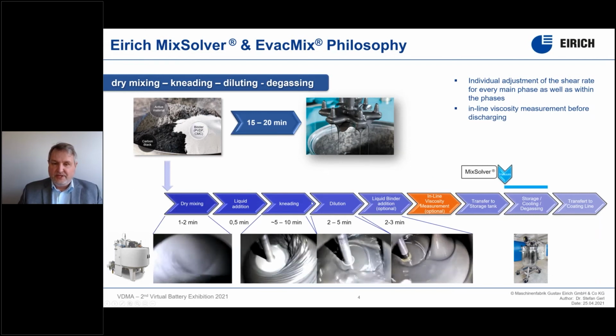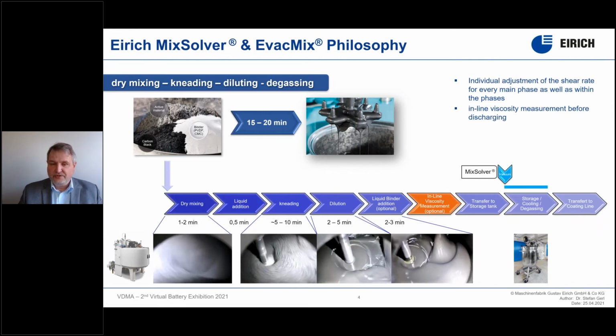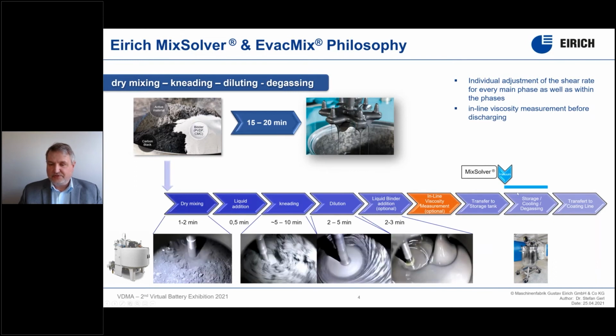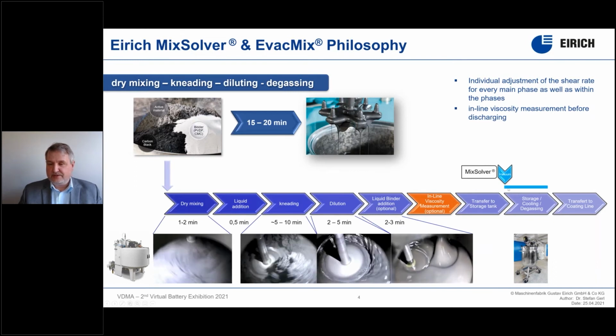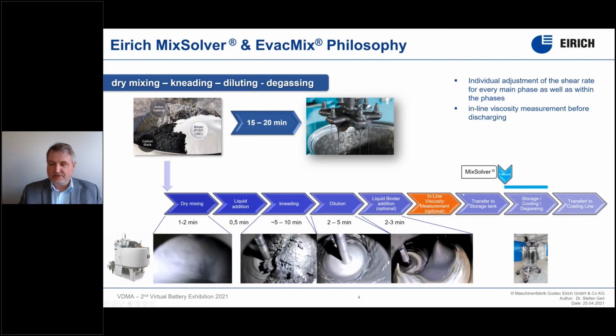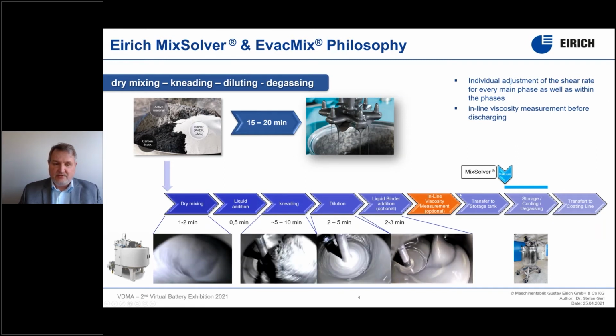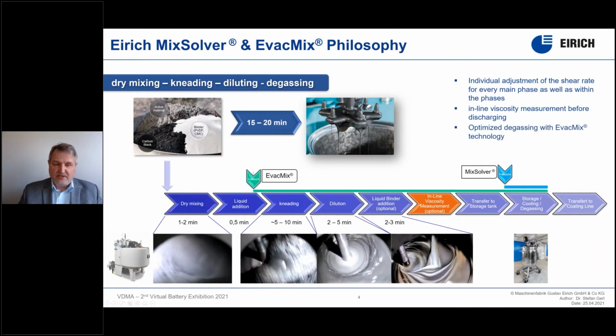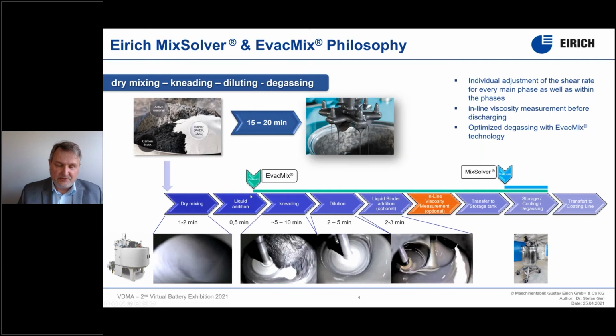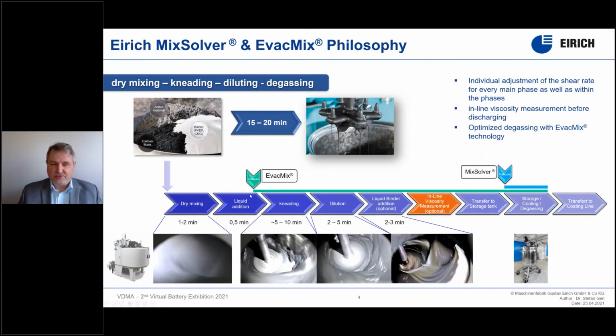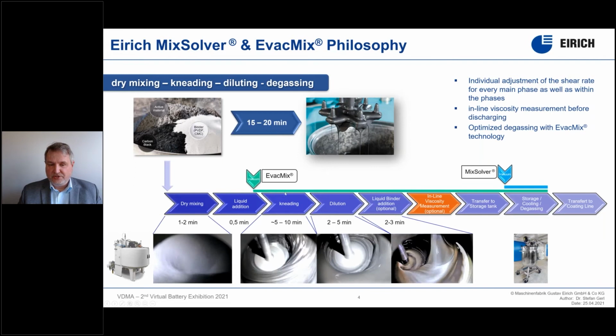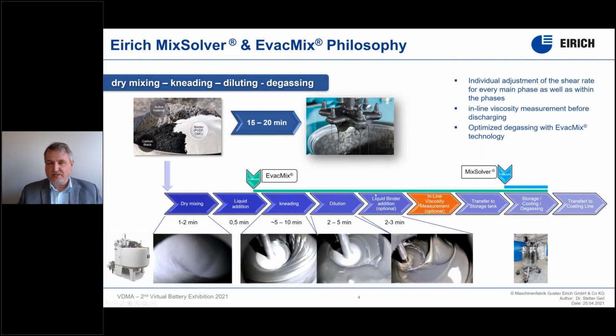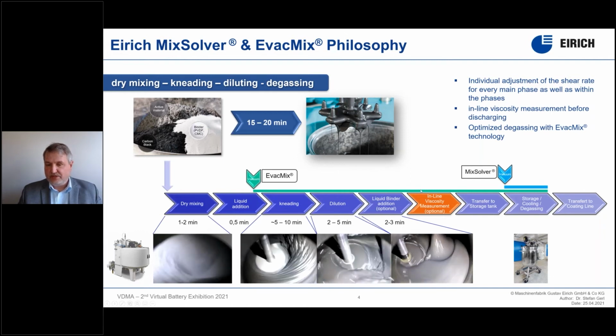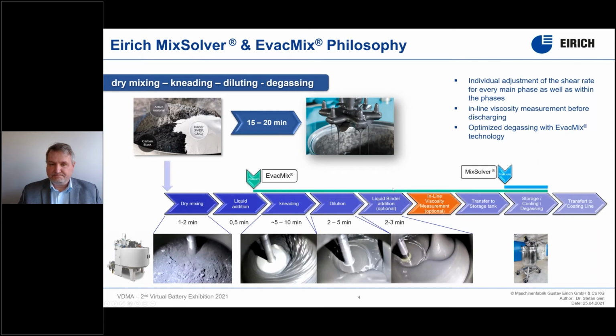If you want to degas, we have two options. If we have a normal Mix Solver with atmospheric operation, we have to do the degassing after transfer to the storage tanks, applying vacuum, and then we are stirring it and taking off the gas bubbles. With a vacuum mixer, an EVAC mixer, we can apply vacuum already at the final end of the liquid addition phase to prevent dust from being sucked out, and then the complete preparation will be made under vacuum, so there are no gas bubbles introduced into the mix, and we have a perfectly degassed product already at the final end.